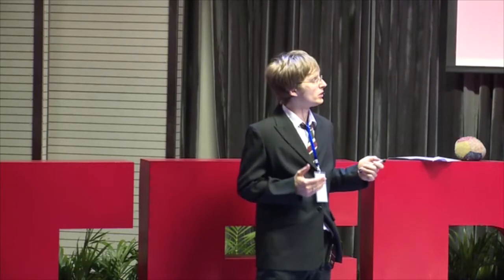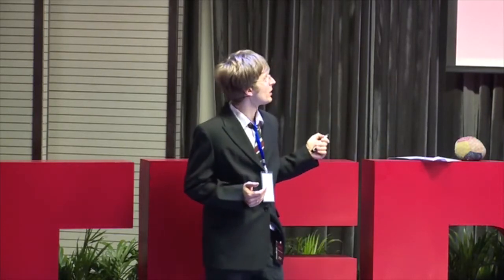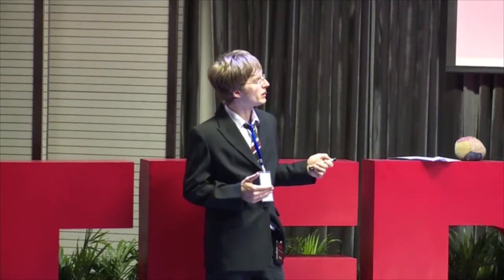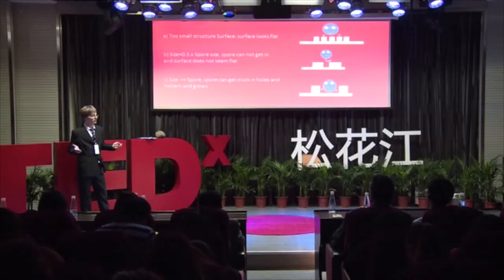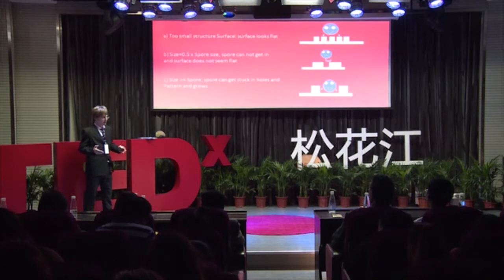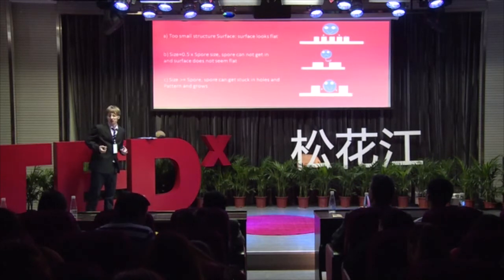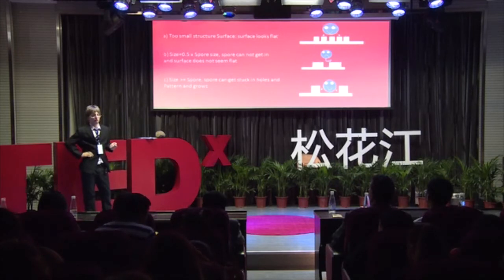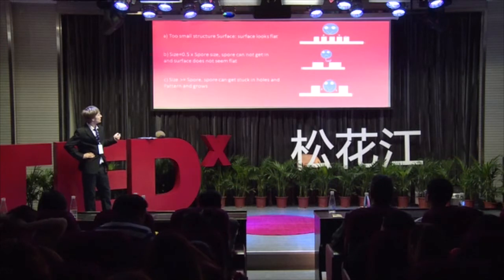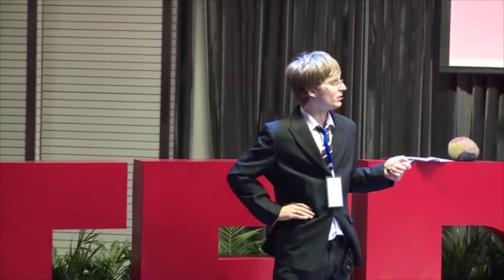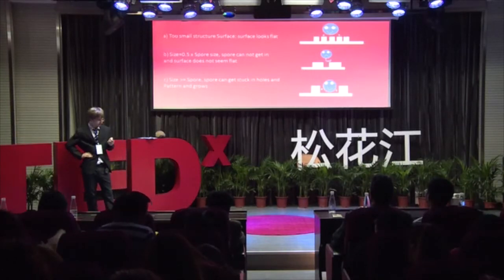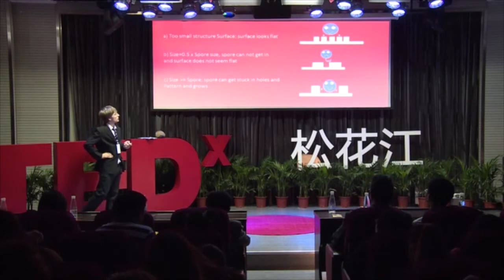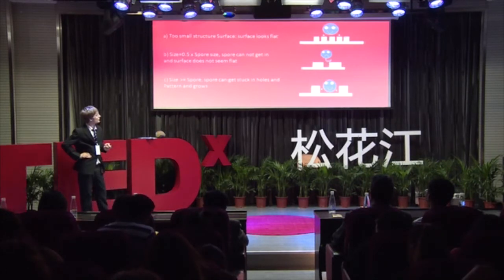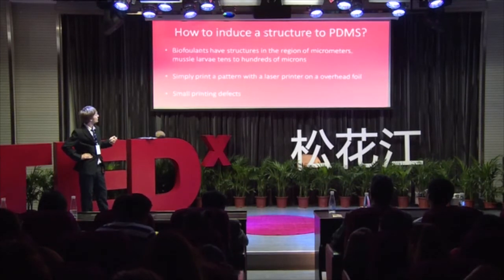Then you put a structure onto the silicone rubber, and if the structure is smaller than the animal, it will still settle, but when the structure is approximately half the size of the animal, then the life form will not settle on it. So you can imagine when you try to lie on a bed and the bed only covers half of your body, it is very uncomfortable and you try to get up as early as possible. Whereas when the structure is larger than the animal, it will feel protected and it will preferably settle on the surface. So this research was also done by some other people, but now here my research starts kicking in.